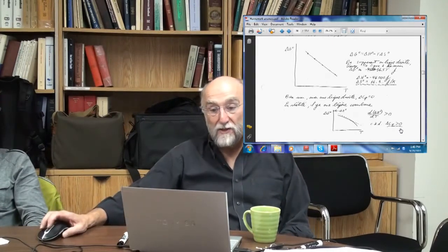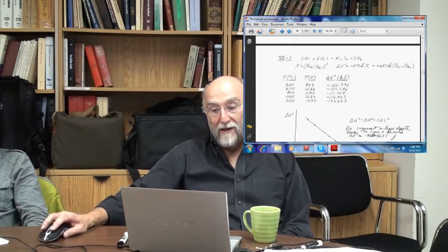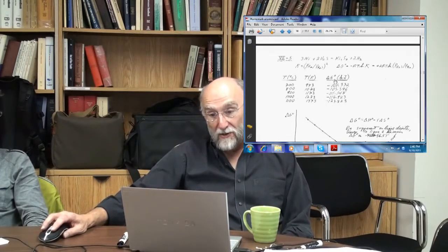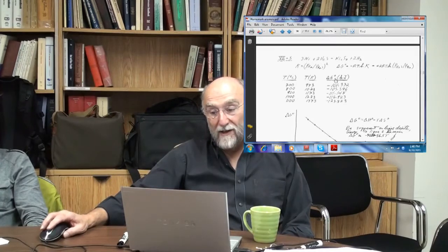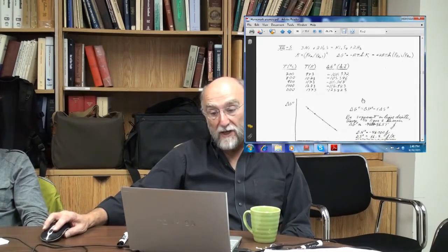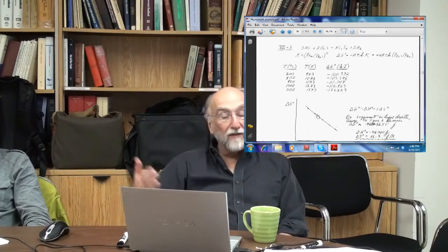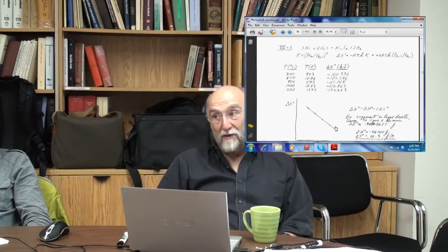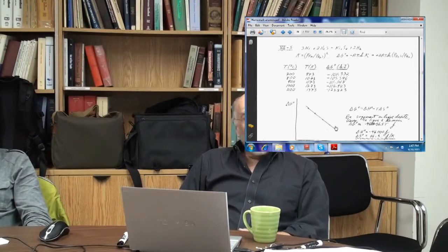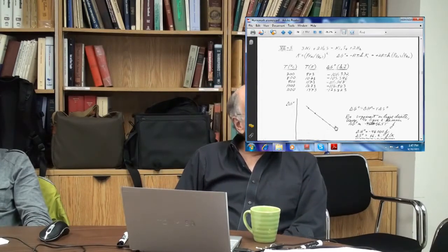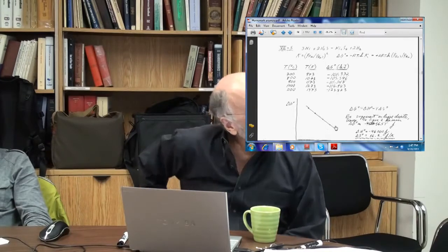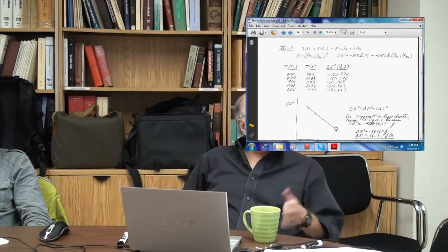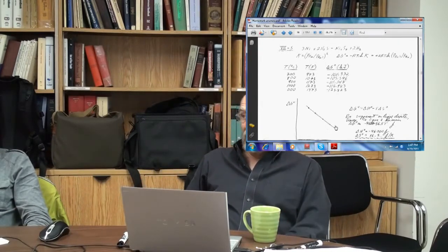So, I mean, this gas equilibration method, what you're measuring is delta G. So delta G0 is quite accurate. Delta H and delta S, which are obtained by the temperature dependence, are the derivatives, so they're going to be less accurate. Delta Cp, which is the second derivative, is going to be even less accurate. So measuring delta H and delta S by the Gibbs-Helmholtz technique is great, but it's not the primary thing you're measuring, it's a derivative, so it's going to be less accurate.